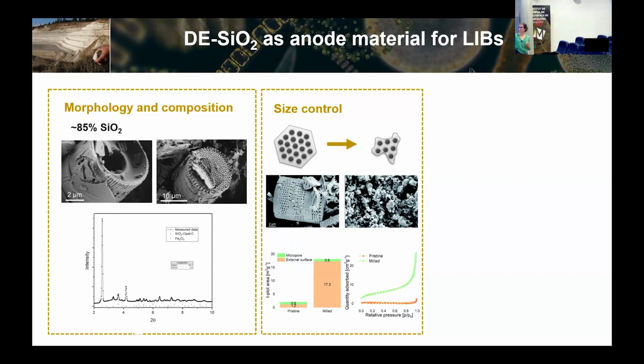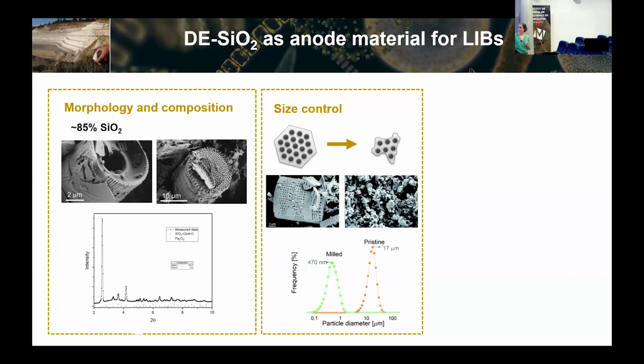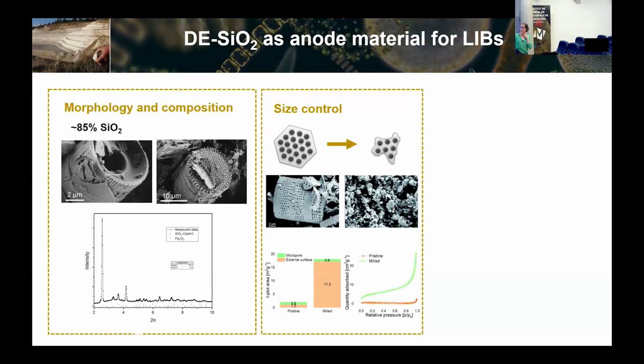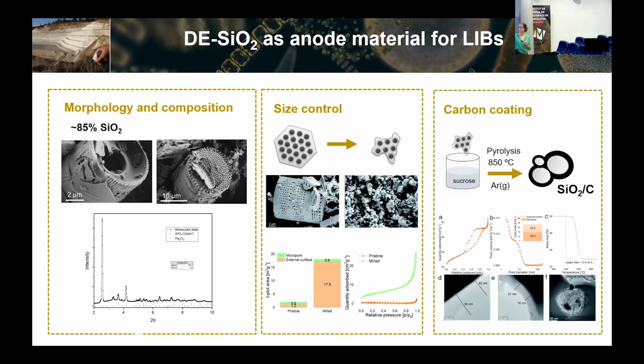If the pristine material had a size of around 20 microns, we can downsize it to 500 nanometers just by doing some ball milling procedures, which is not easy because diatoms are actually harder than the milling balls. So we end up with the situation that diatoms are milling the balls. That's also something we learned about the mechanical properties of this algae. And by doing ball milling, we can increase the surface area quite a lot. So that could be a good thing.